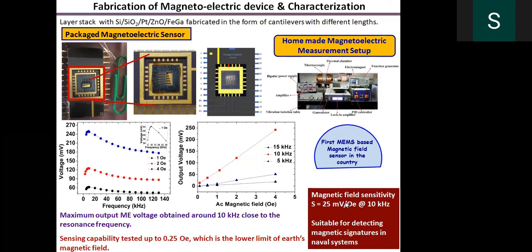The magnetic field sensitivity has been found to be less than 1 oersted. I mean, the magnetic field sensitivity has been found to be 25 millivolts per oersted at 10 kilohertz, which is the resonance frequency, and these devices are found to be very much suitable for detecting magnetic signatures in naval systems.